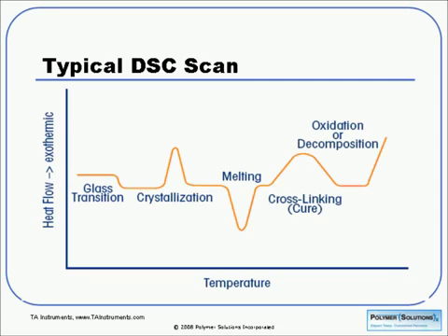So here we see a hypothetical DSC scan. Our y-axis is heat flow, and in this case, exotherm is pointing upwards. That's important to note because some people use the opposite sign convention, so you want to be sure you take note of that when you're looking at a DSC scan. Our x-axis is temperature, and we see that as we are increasing the temperature, we see a step towards the endotherm, and that's how TG looks on these scans.